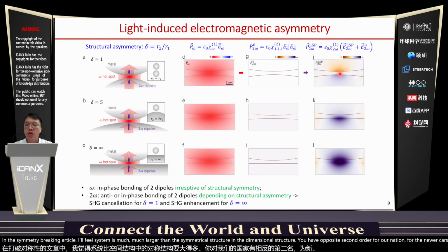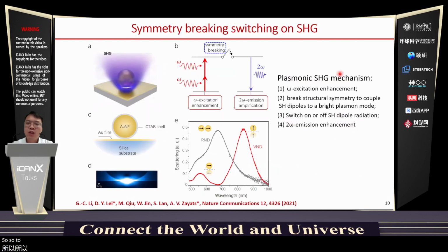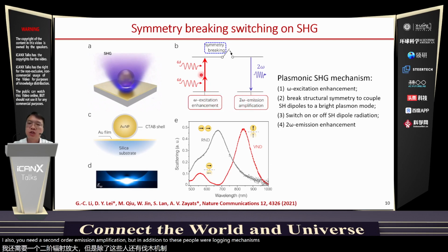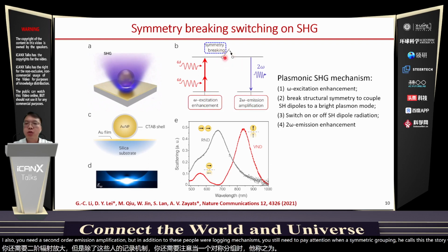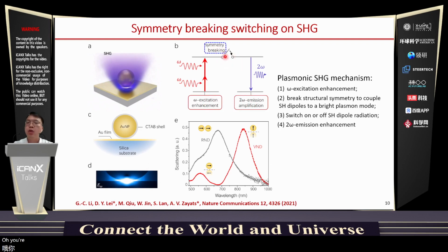You will cancel out. So to summarize our argument, now we put forward this full picture for second harmonic enhancement in plasmonic nanostructures: you need fundamental excitation enhancement, and also you need second order emission amplification. But in addition to these two well-known mechanisms, you still need to pay attention to the symmetry breaking, because this symmetry breaking can switch on your second harmonic dipole coupling, or switch it off, to give you a very large second harmonic emission signal or cancel out the second harmonic emission.